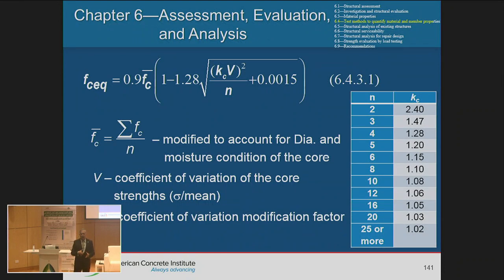Well, as an engineer, when you specify on your drawings, I need 40 MPa, the batch plant will design the mix not for exactly 40 MPa, but for 48 MPa. And they go through the statistical analysis to reduce it down to something that is measurable with 40. The same thing here. You see on that table, we have the coefficient of variation, and we also have these factors. So as the number of your cores increases, that factor decreases.